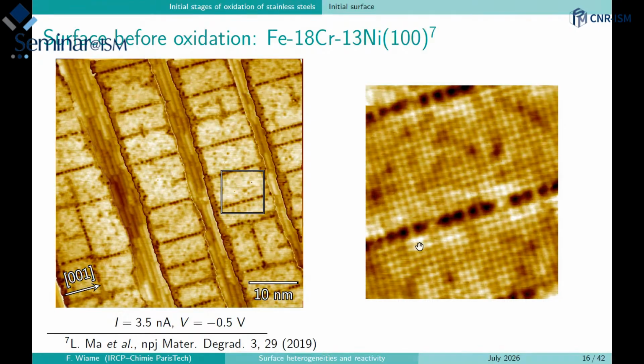If we are now focusing and trying to understand why we have these vacancy lines, you can see that in fact the width of these vacancy lines is, if we go from this atom to this atom, 3 lattice parameters, which in fact corresponds to 2 missing rows of atoms.